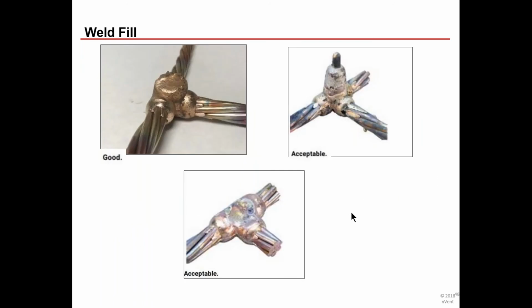So here are some examples of acceptable welds. This is a very good one, nice gold patina. This one is acceptable even though it looks kind of ugly. This right here, where you can see the different color change, is all slag. That slag can be knocked off, and it would probably look something like this. There's a little bit of depression, but as you can see, it still completely covers the conductors. So this could be considered acceptable, and it's not pitted where there's a lot of slag in there. It still looks pretty much like copper, so it can be an acceptable one.